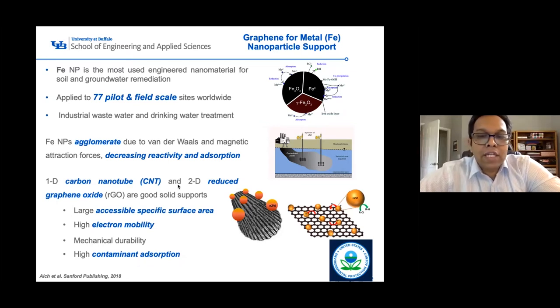So what we can do is put them on carbon-based supports like carbon nanotube or graphene, either two-dimensional or one-dimensional structures, where these carbon-based structures can give large accessible surface area, but at the same time, they are carbon-based, so they will attract different types of contaminants. They also have high electron mobility, so when these iron nanoparticles release the electrons, they can move very fast and will enhance the reactivity. So including all this, it becomes really attractive for us to study this.